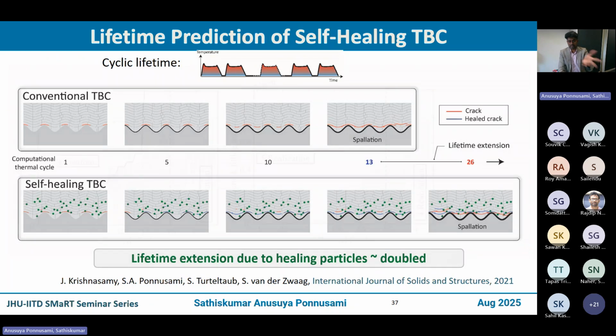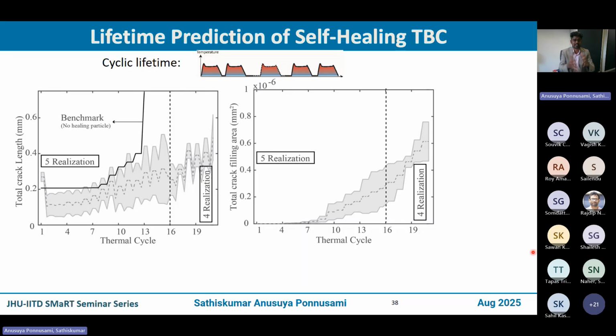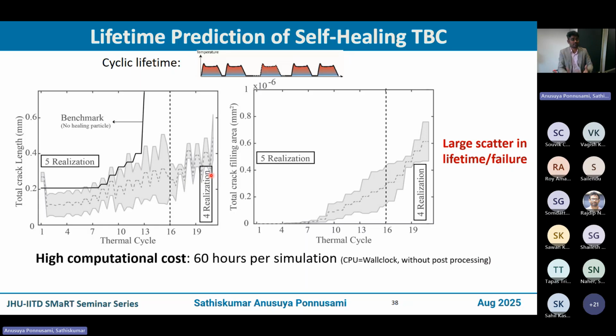The reason for that is the statistics of crack evolution. It's quite stochastic, in the sense that it's not really deterministic. But what you see is, compared to this black line, which is without healing particles, if you put in healing particles, the slope goes down, which means you're slowing down the crack growth and the number of cycles increases. That is the effect of self-healing. But then there is a large scatter. So how do you handle that scatter? If you want to do a Monte Carlo simulation, it's quite impossible because each simulation took 60 hours on the high performance computing cluster, and we are talking about thousands of simulations, which we cannot really afford to do.